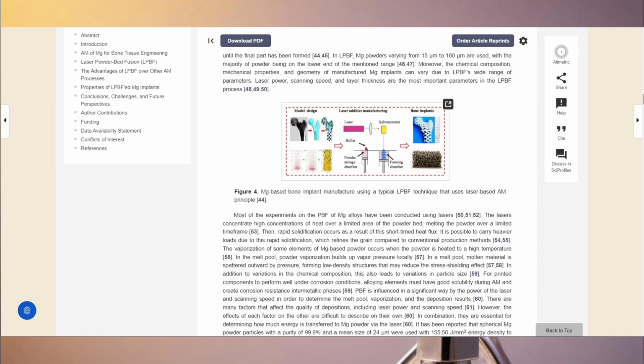During laser-based PBF of magnesium, a concentrated heat source melts the powder briefly, followed by rapid solidification. Compared to conventional methods, this quick melt and solidify cycle refines the grain structure. However, at high temperatures, some elements in the Mg powder, magnesium powder, may vaporize, creating a buildup and increase of vapor pressure in the melt pool. The pressure can spatter and scatter molten material outward, forming areas of lower density that may help reduce the stress shielding effect in our bone implants.